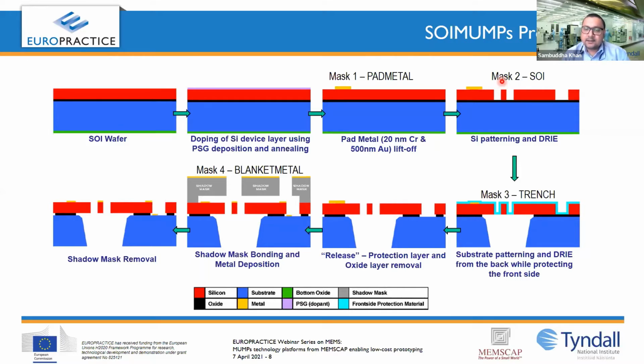Once that is done, you need to release it. So you remove the protection layer, and the oxide layer is also removed by vapor HF. And so the device is almost ready. Only one mask, the blanket metal mask, is left. Blanket metal is for those who need bigger pads and a very reflective surface, like for optical devices. The blanket metal mask is used to develop a shadow mask using silicon, and that shadow mask is bonded to the processed SOI wafer, and then chrome gold is deposited again. Once that is done, you remove the shadow mask and your device is ready.